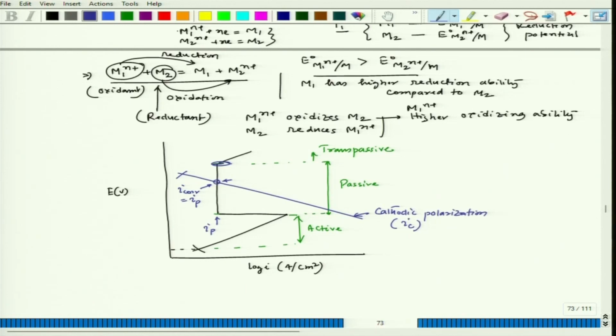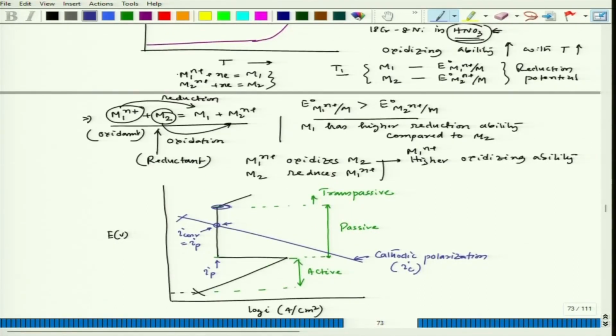Now, if we increase temperature, what happens? The oxidizing power increases. As we have seen, a higher reduction potential means higher oxidizing power. So, oxidizing power increases means its reduction potential also increases. So, the reduction potential goes up. Since it is close to, and as we go up, it will have its own corresponding polarization plot, and we could see that it is cutting at a different location, and it is quickly getting into the transpassive zone.